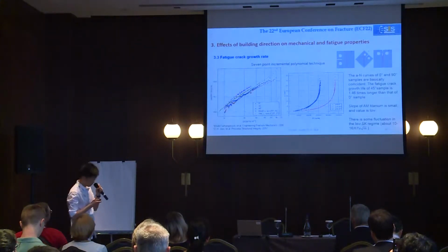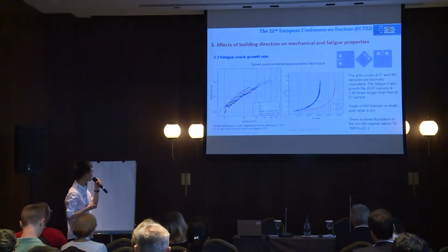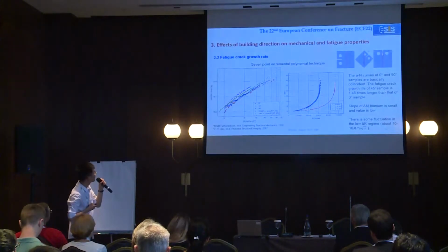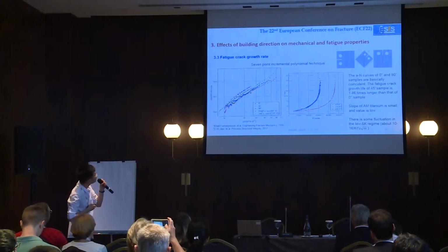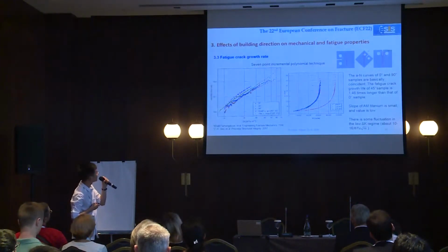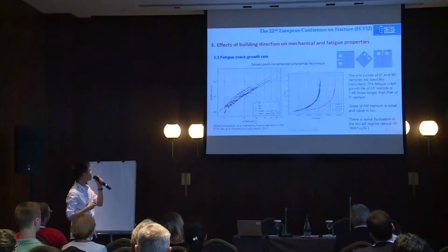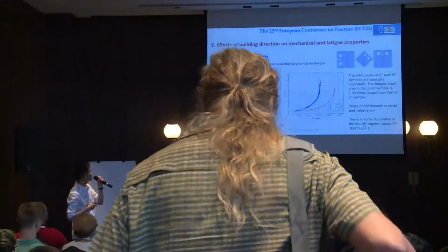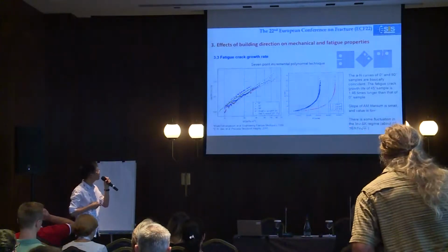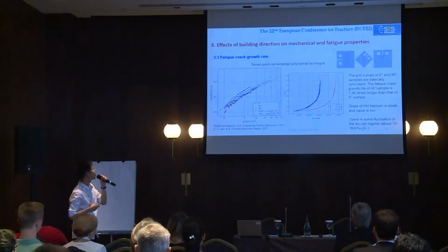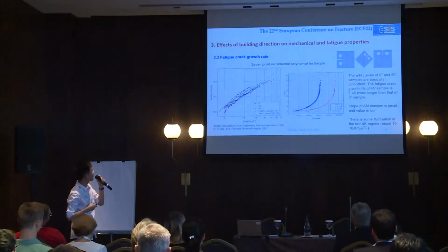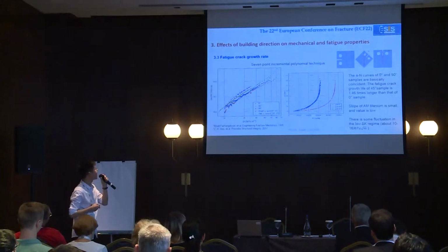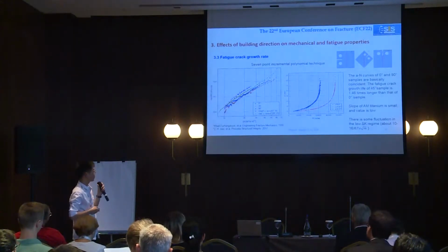And then the a-N curves are obtained in this picture, and it's apparent that the a-N curves of 0-degree samples and 90-degree samples are basically coincident, these two lines. And the fatigue crack life of 45-degree samples is 1.46 times longer than that of 0-degree samples.